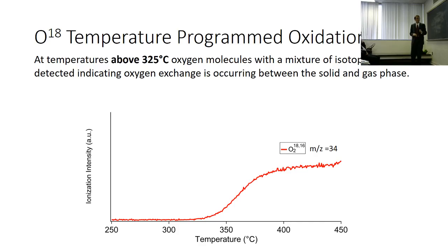So I did the experiment, and that's exactly what I saw. Just around, at temperatures above 325 C, you start to see this trace in the mass spec of a molecule of oxygen that contains one O18 atom and one O16 atom.